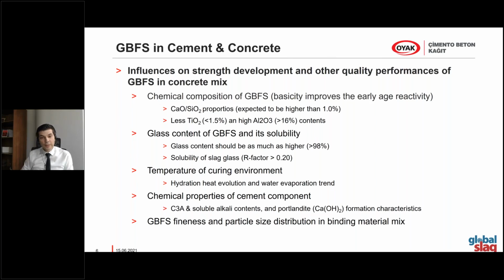The chemical properties of the cement components are also critical. While producing GBFS blended cements, we check their adaptation and compatibility. In the ready-mix stage, we also produce and make our designs according to the specific recipe requirements. GBFS fineness and particle size distribution are also critical, and we adjust them; this is one of the critical parts.